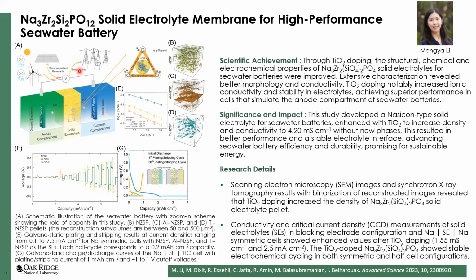However, it is very hard to get membranes which have good properties for both the organic as well as the inorganic, the aqueous as well as the non-aqueous portions of it. So tailoring these solid electrolyte membranes is a very productive area of research. Monia has been doing that. She has made a device using the so-called NASICON electrolytes, where she has shown significant improvement in properties by just adding titanium dioxide to it. This was extensive work which was published recently.